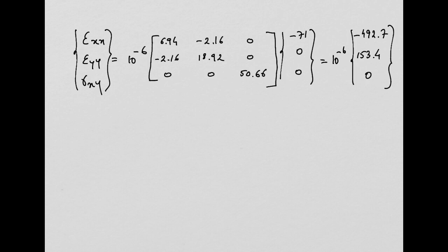So this is what you get once you build that laminate with three plies. Two plies at plus 60, minus 60 degrees fiber orientation, the other ply at 0 degrees. We built the stiffness of the entire laminate, we inverted it to obtain the compliance matrix, and then we multiplied that compliance matrix by the given stress tensor to obtain the deformation tensor of the entire laminate.